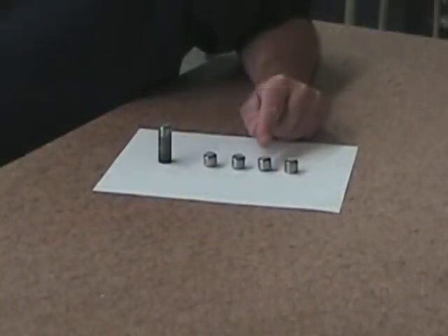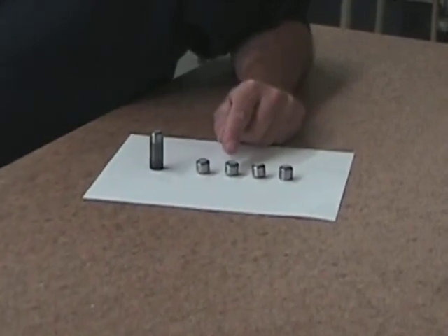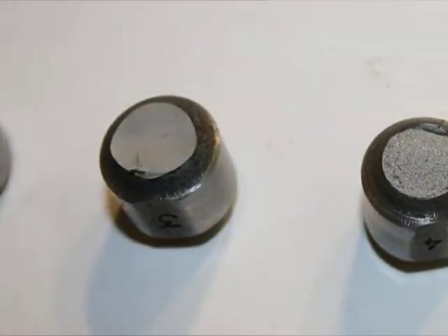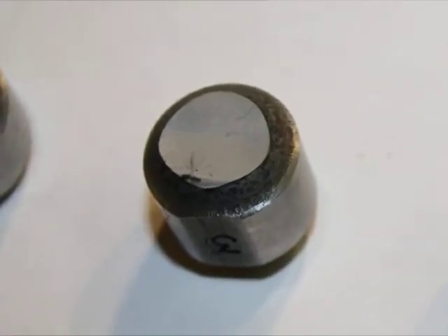We also notice the grain structure of the different segments. If we look at the grain structure of the first segment, we notice that it's quite coarse. The second segment, a little less coarse. Even though it was easy to break, the grain structure is getting a little tighter. The third section has a very tight but smooth grain. It is actually the segment that has the best treatment in it. It is as hard as segments 2 and 1, but it has a grain structure that will give it maximum toughness with its maximum hardness.